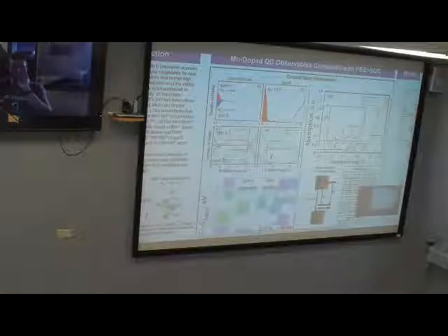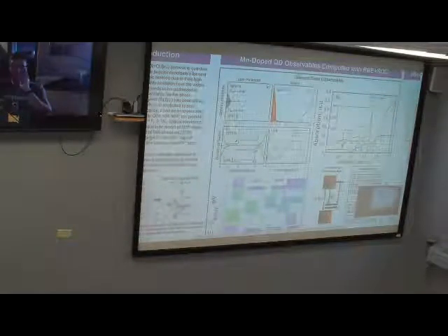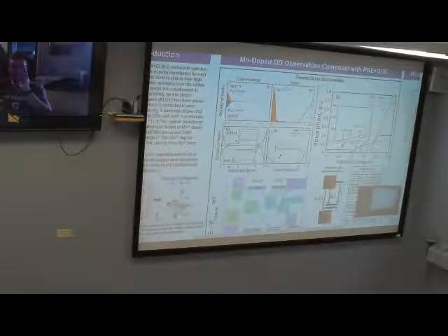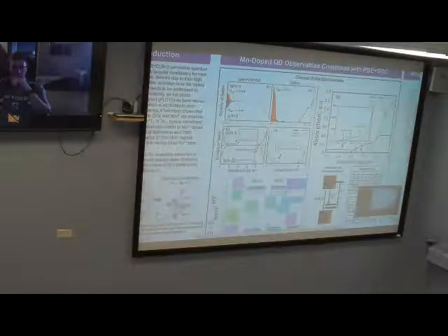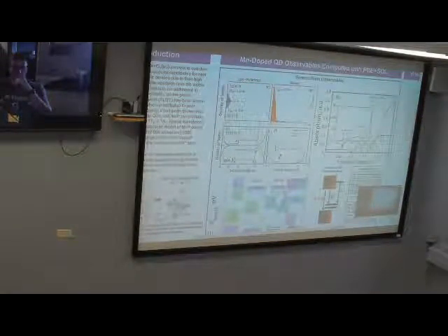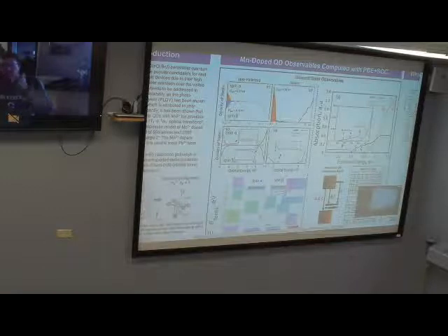A question. For an intrinsic perovskite with no dopants, does the basic electronic structure look reasonable by using PBE plus SOC? Yeah, so with perovskites you get a qualitatively correct band gap. Well, I take that back. If you don't use spin orbit coupling, you get qualitatively correct band gaps for the size of the material you're looking at. So this one just happens to look experimentally correct just due to the spin orbit coupling. So having the correct band gap is kind of just an accident. A nice accident, but.